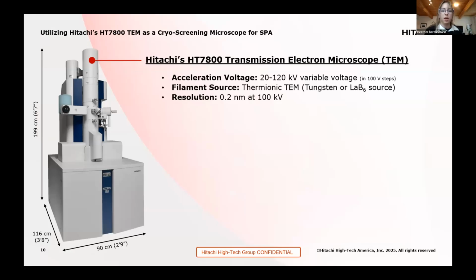And so rather than using a field emission source, this is now a thermionic TEM, meaning it uses either a tungsten or a LaB6 source. And then the resolution is about 0.2 nanometers at 100 kV. And so with this type of microscope, it enables more affordability to purchase a thermionic system rather than a field emission one. And also the cost of maintenance and ownership is decreased as well.